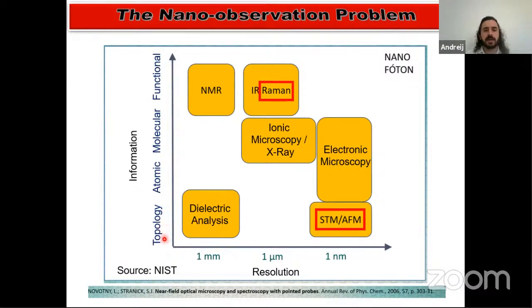The dielectric analysis is here in the macro world, which can unravel only topology. But if we walk along the x-axis, we find the STM and AFM techniques, which have nanometer resolution but only show topology information. If we go above, we find electron microscopy, which now unravels atomic and molecular information of the systems. And if we go back on the resolution, we find ion microscopy and X-ray. And going above again, we find the famous optical techniques such as IR, infrared, and Raman spectroscopy. These are really nice techniques because they give very detailed information about matter, but they are limited by the diffraction of light. So we can only go to 1 micrometer resolution.